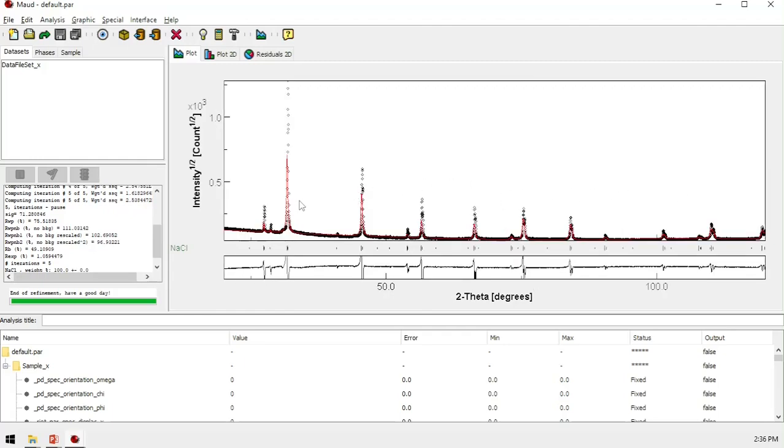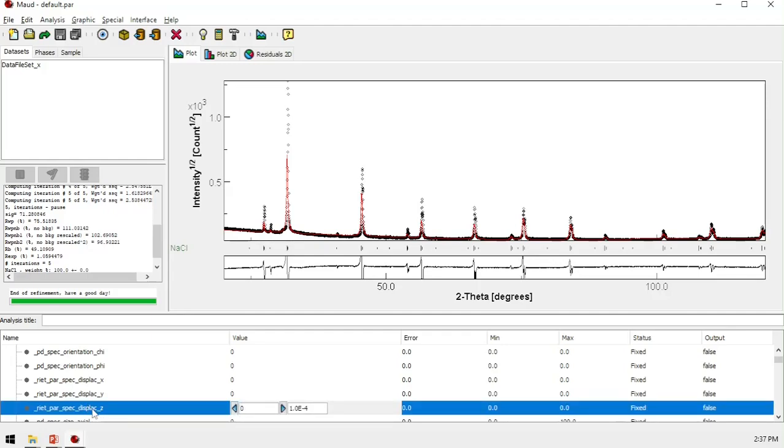One of the possibilities in this measurement is that the sample is not at the correct height when it's prepared. To refine and correct it, we will compensate the position of the diffraction pattern. In a simple way, the sample is too close to the detector, so we can adjust this displacement of z, the height of the sample,